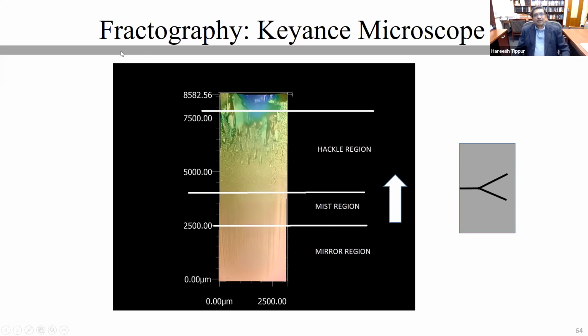So here is a fractographic image from a digital microscope. This digital microscope is a Keyence microscope. Some of you may have worked on this. Here I'm showing the surface of the fractured glass from a single bifurcation experiment. The crack is propagating from bottom to top. The lower part here is your mirror region. And typically in the dynamic fracture mechanics literature, you come across these mirror, mist, and hackle regions as the demarcations of the phase of the growing crack.